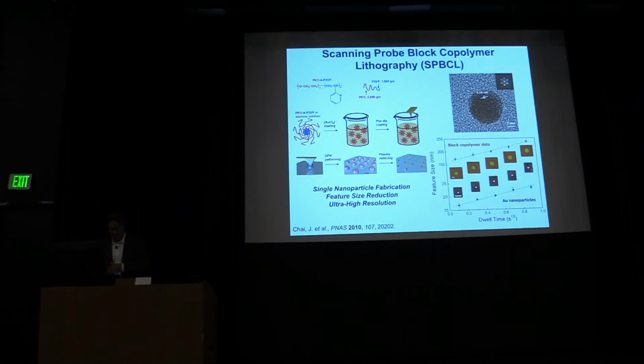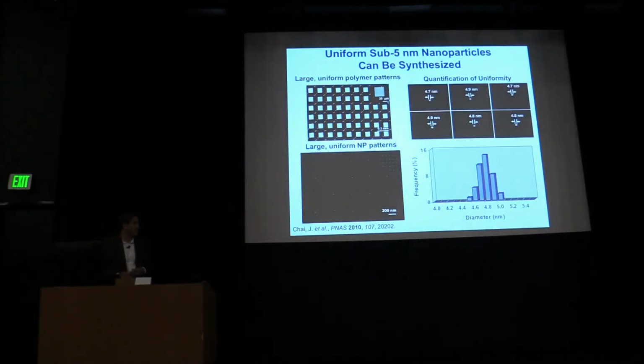It didn't necessarily have to be the case, but that turns out to be the case, and that turns out to be quite useful. This is massively parallel. So now we can make millions using the PPL array, in this case all designed to be sub 10 nanometer in size. We can go to very, very small, as you're going to see: 4.8 plus or minus a tenth of a nanometer. For those of you up front, you can see a little bright spot here. These are the particles that form in each of the reactors. Okay, so all the atoms, again, going and forming the particles.